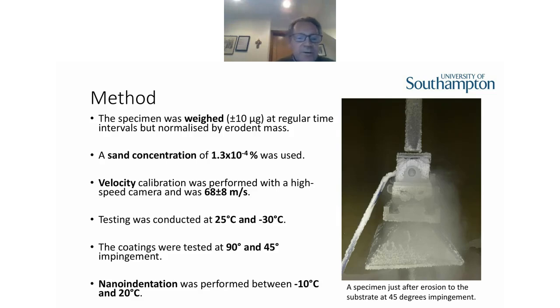So this is a fairly basic test. You weigh the sample before. It's quite difficult with polymers. So we weigh as accurately as we can to try and get some assessment of volume loss per particle impacting. The sand concentration, as you can see there, is 1.3 × 10^-4 %. The velocity was calibrated using a high-speed video camera, but with the size distribution of the sand that I mentioned, it was somewhere between 60 and 75 meters per second.